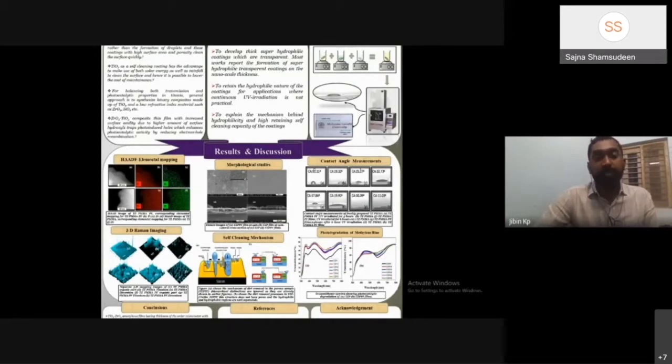And thus we can conclude the mechanism behind the titanium zirconia films. We have two types of mechanisms. That means a photo-induced superhydrophilicity is observed here. First, the presence of TiO2 generates electrons and O2 minus ions, and these will degrade the dirt and break it down into small molecules, and the sheeting of the water due to the hydrophilic nature will clean the surfaces.